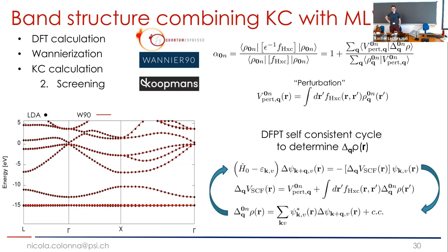But again, to do phonons, I think it would be simpler to do finite differences with phonopy than trying to do a Sternheimer equation on top of that. Exactly, as also in DFT plus U. Yeah, there are phonons in DFT plus U with linear response, but it's so much easier to do them by finite differences. If you want, there is one additional concept: this screening coefficient is configuration dependent. So when you take the first or the second derivative of the total energy, you should in principle take into account that the screening coefficient is also configuration dependent, so it contributes to the phonon frequency, and that makes it a little bit more complicated.